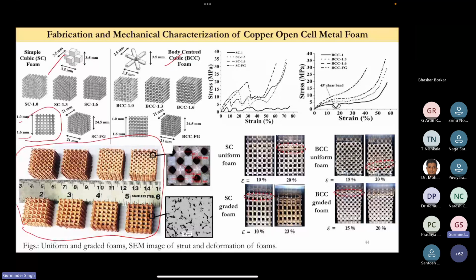And we have seen there is a beauty in having two different types of pores. One, you can have design pores, okay, which come from your CAD model. Another porosity is micropores, okay, which is at the strut of the 3D printed forms. So these micropores can be controlled. You can have fewer micropores, you can have more micropores. It gives you an advantage, like if you are making it for biocompatible applications, okay, for example using titanium Ti6Al4V, you can have better cell adhesion. If you're using it for corrosion activities, you can have fast local corrosion because you have microporosity. So it can be used for a number of types of applications.